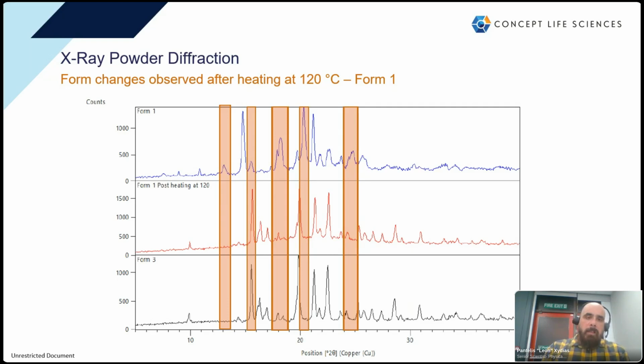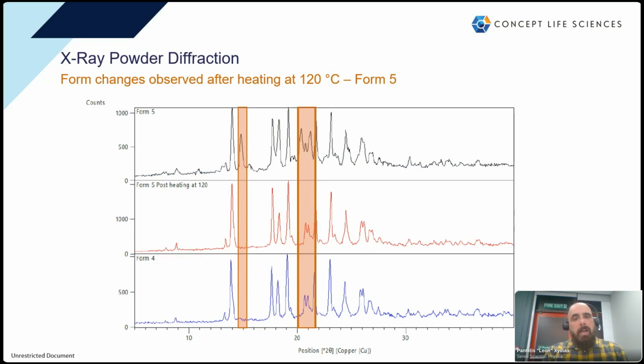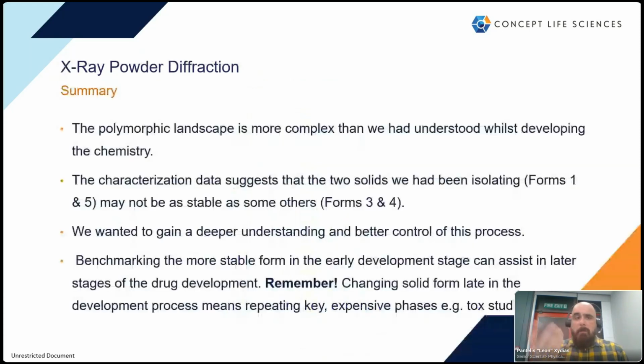The same thing happened to that Form 5 that we isolated. What prompted us to believe that it is actually a mixture of the two forms is the fact that after we heated it at 120, this time we got Form 4, which made us believe that Form 1 is formed and converted to Form 3 as we heat it up, whereas Form 4 remains stable after being heated up. So just to summarize briefly, this experiment showed that although we at first expected Form 1 and Form 5 to be the most interesting ones we were targeting, nonetheless, the polymorphic landscape was more complex, and we were able to identify that we probably have 2 more forms, Form 3 and Form 4, which are more stable.